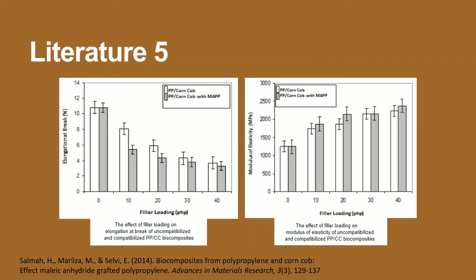A similar trend has been observed for the elongation at break shown in the figure on the left for the uncompatibilized sample. This is due to a weaker interfacial region between filler and matrix. Lastly, the effect of filler loading on modulus of elasticity of the uncompatibilized polypropylene and corncob biocomposites is illustrated on the figure on the right. It can be seen that the modulus of elasticity increased with increase in corncob loading. An increase in the modulus of elasticity indicates the stiffness of the biocomposite samples. Overall, the compatibilized biocomposites have higher tensile strength and modulus of elasticity compared to the uncompatibilized biocomposites.